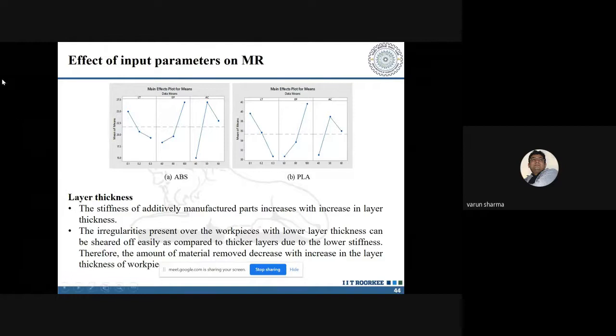Now, similarly, whatever irregularities are present at a relatively lower layer thickness can be easily sheared off because that had a lower stiffness. That was the reason that for 0.1 mm, the material removal was on a higher side. Similarly was the case with the extrusion pressure: as the extrusion pressure increased, the material removal increased gradually.